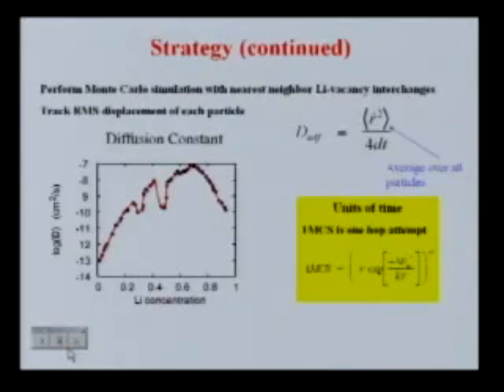Here's an example of how that works out. If you calculate barriers in lithium cobalt oxide and then do a kinetic Monte Carlo simulation, keeping track of the root mean square displacement, you get the macroscopic diffusivity. As you see, it varies by orders of magnitude: 10 to the minus 7 centimeters squared per second here, and 10 to the minus 13 here. You can already see that you would never get to these time scales with a simple dynamics model.